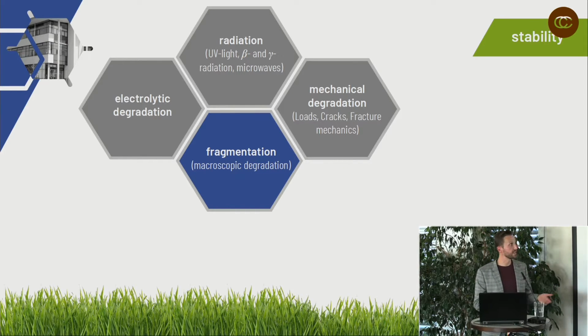Yeah? So this can lead to cracks, to further crack propagation, to fracture and to a break and a failure at the end of the day. We have electrolytic degradation. These are so-called physical degradation processes. And these also happen in the ocean, for example. That means the waves and the stones inside the oceans lead to mechanical degradation, and we have UV light there. So this leads to fragmentation.